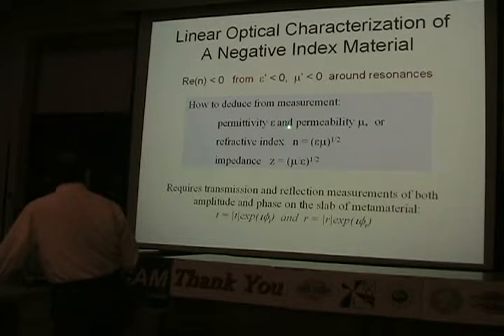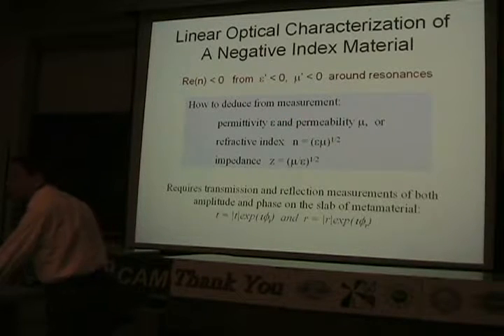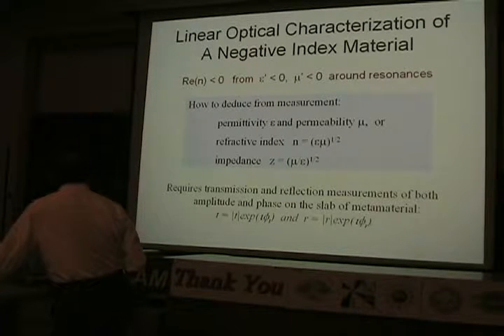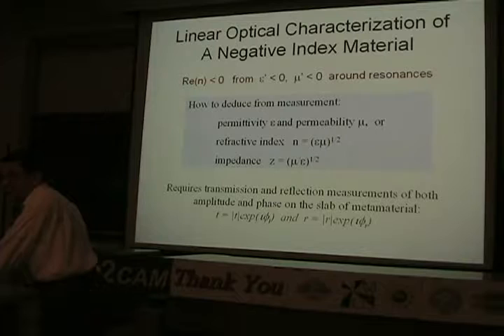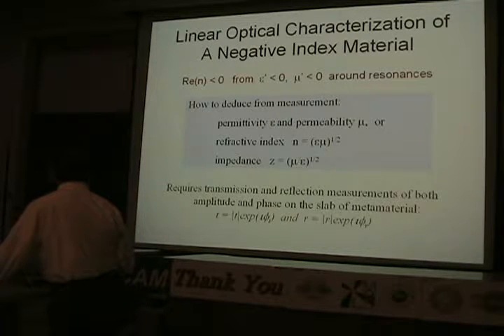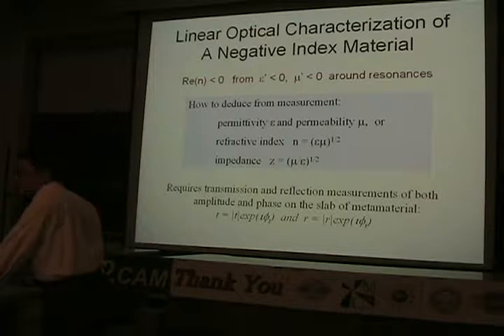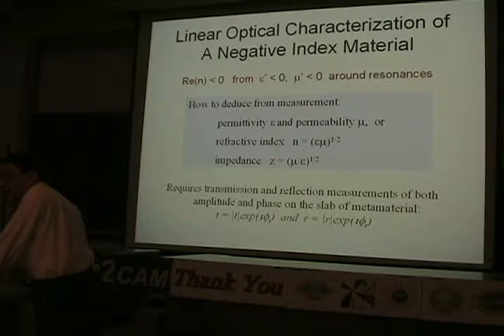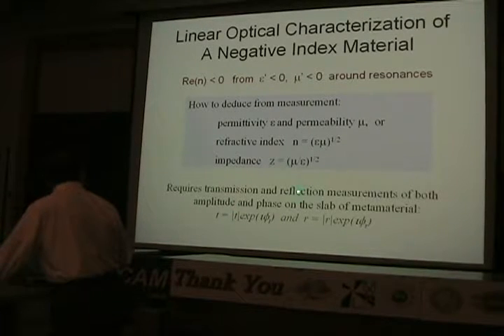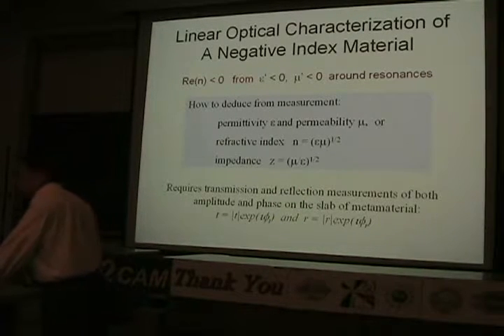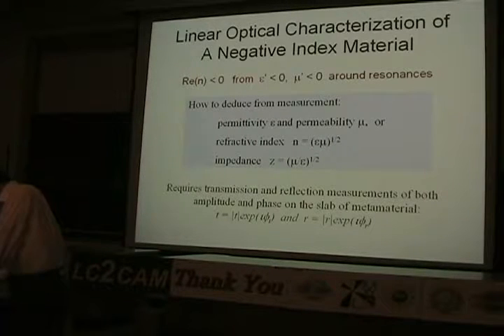And all these quantities are complex quantities. Both real and imaginary parts are there. So you need four measurements. And clearly, if you do transmission and reflection measurements, you get intensity measurements, and these are two quantities, but you also need the phases, and that gives you another two quantities. So you can measure transmission, reflection, intensity, and the phases, and that will then determine the four quantities you want.